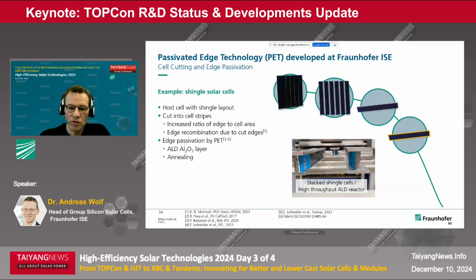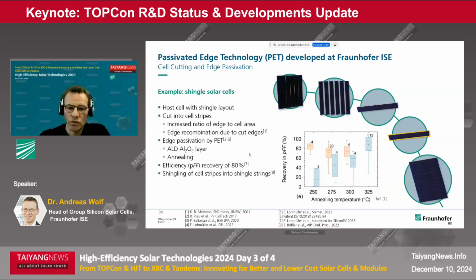This might be a high throughput approach where you stack, in this case, shingle cells and passivate the interfaces, the edges here with an ALD aluminum oxide layer and subsequent annealing. And this is also an approach where we hold a German patent, and it enables to recover most of the efficiency losses that are introduced by cutting the cells into stripes.